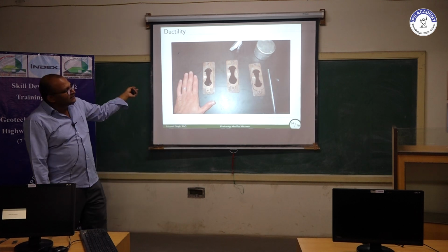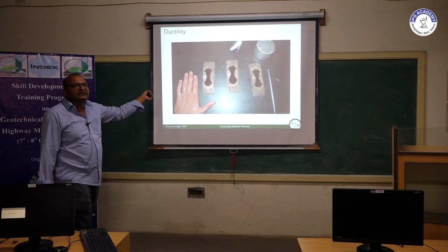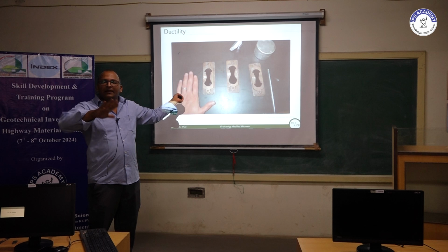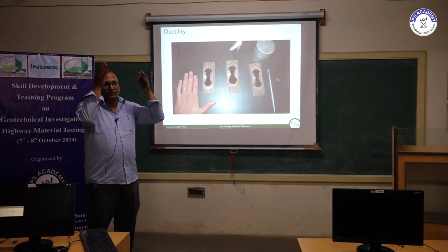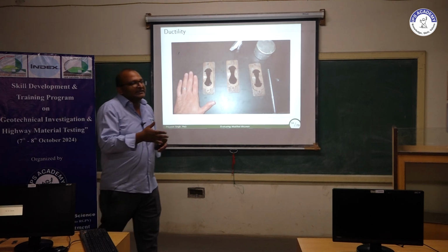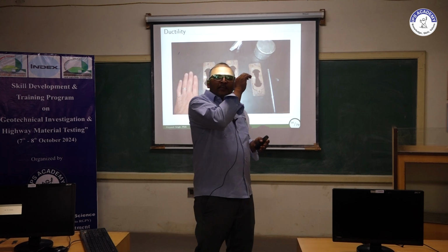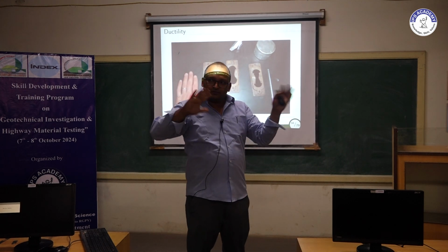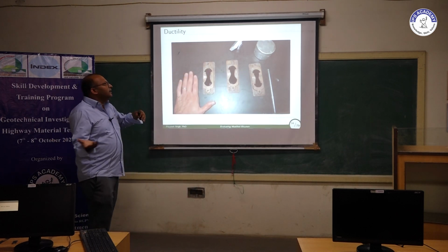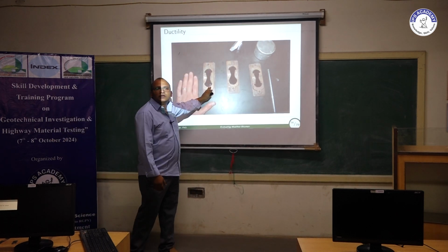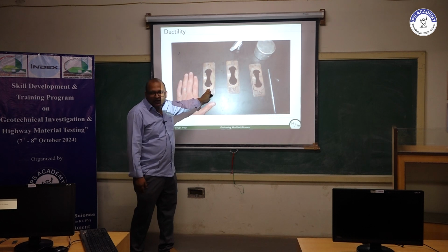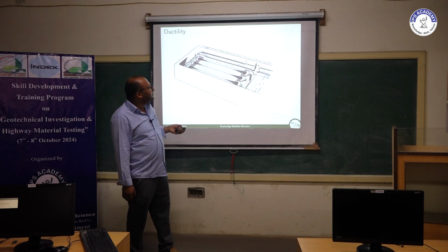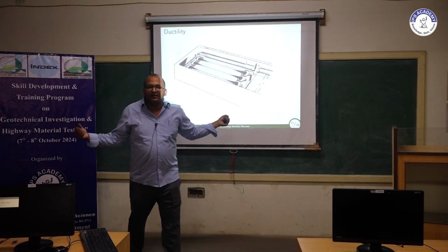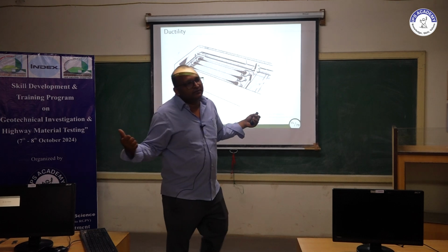Then the ductility test. Now I have kept this ductility test on the unaged sample only, but the 2013 version of IS 73 has kept this test after short term aging. So just take care of this. In ductility, we will put our binder in a standard briquette, and then we will try to stress it at a standard rate. Now what property does this signify?